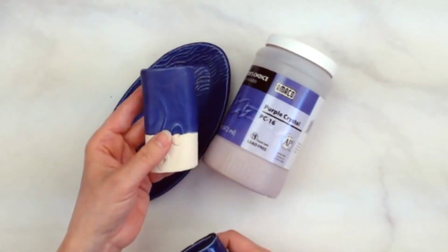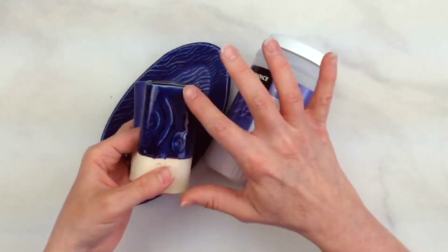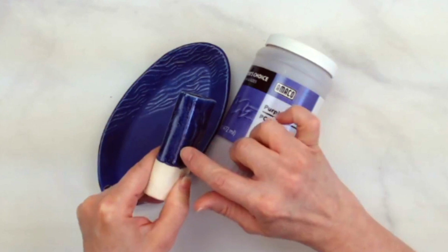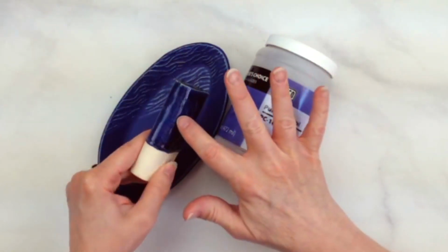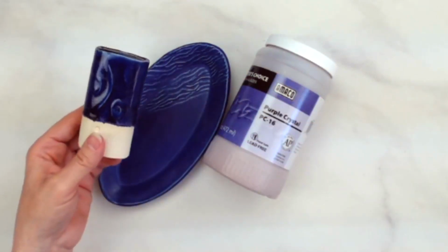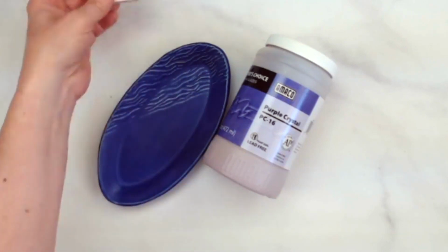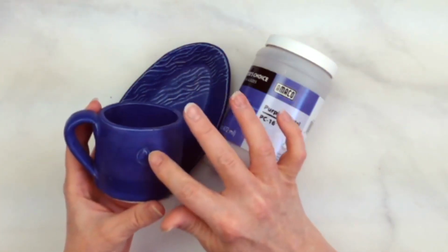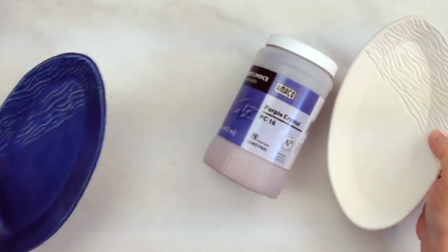I'd like to show you, this is cone 5, purple matte. This is cone 6. So at cone 6 it becomes more glossy, but it also develops these purple microcrystals, which is what it's doing here to make it matte. It's a microcrystalline matte. The crystals are not like large macro crystals, they are tiny microcrystals, but if you look at them very closely, you can see they are indeed crystals, just like snowflakes. At cone 6 it starts to show those microcrystals as a speckle across the surface. Really lovely. But even at cone 5 with this gorgeous satin matte, it's getting this kind of pale blue where it breaks. Pale blue to clear.